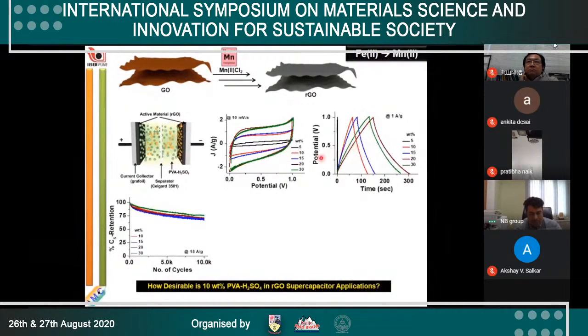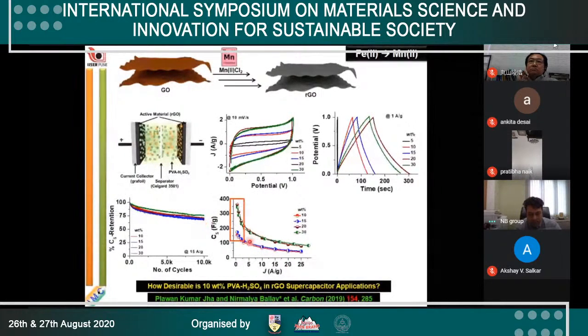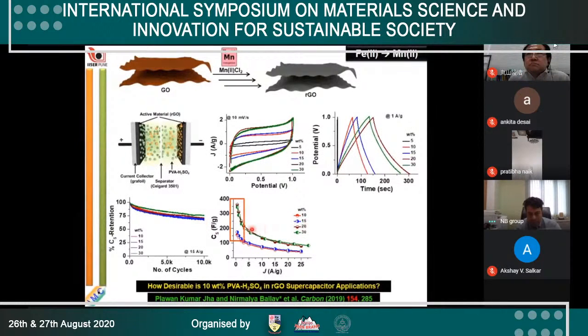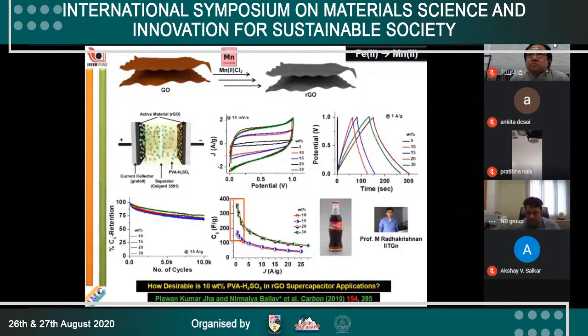This is CV and this is CD. What is apparent is all are pretty stable in capacitance retention. However, when you look at the capacitance value, look here, 15% and 20%. The values are almost double. Just by adding a few drops of water more into the system, the rest being identical, we could significantly enhance the capacitance value. It reminds me of the story of Coca-Cola. More than 90% is just water. My friend Professor M. Radhakrishnan from IIT Gandhinagar is looking at this unusual aspect of water in the supercapacitor performance from the theoretical perspective.